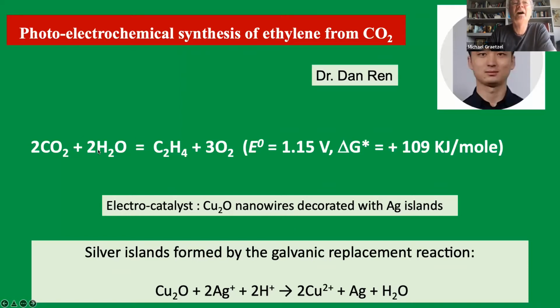And you see, if you write this reaction down, the conversion of CO2 to ethylene, well, how many electrons do you need? Well, it's a 12 electron reaction. Making 1 molecule of ethylene requires 12 electrons and 2 CO2 molecules. It looks like a very complex process, and you wouldn't give it a lot of chances from the electrochemical point of view. But copper does it. The copper is actually an invention by Professor Hori from Japan many years ago. He found that copper is the only metal where you can make alkanes from CO2 with significant Faraday efficiency.